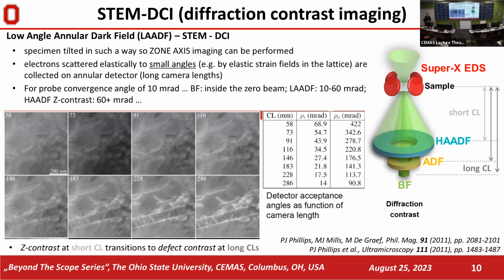So that's a huge advantage that you have your crystal tilted in zone axis, and you can transition from Z contrast, eventually atomic resolution, to defect contrast just by switching the camera length.